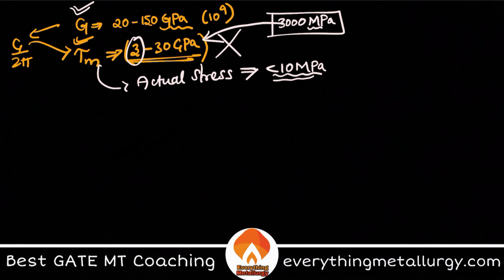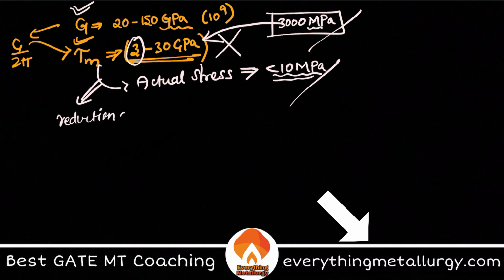But the actual shear stress value needed for plastic flow, plastic deformation, that means for slip to take place, is less than 10 MPa. So here comes the discrepancy. There is a discrepancy in the shear stress values. Experimentally you are getting such low values, whereas theoretically when you calculate, you are getting way too high values. You can see less than 10 and 3000 MPa. So this particular reduction of shear stress has actually been observed experimentally.